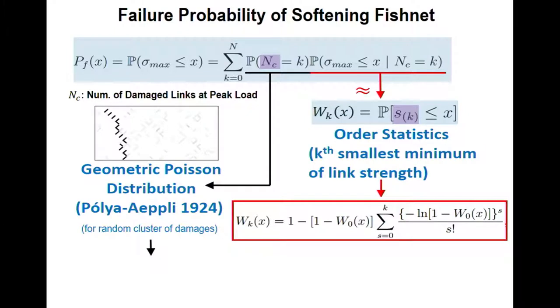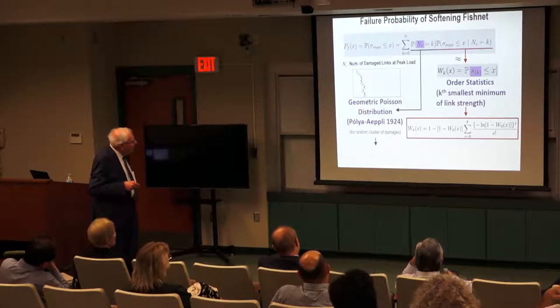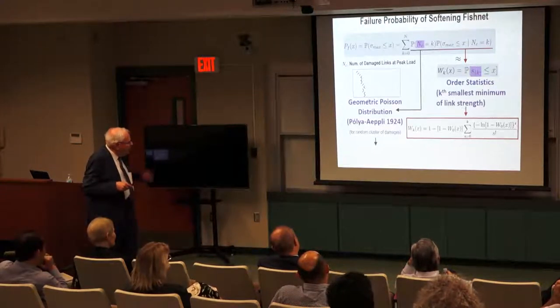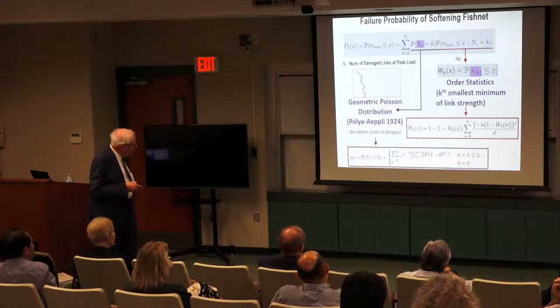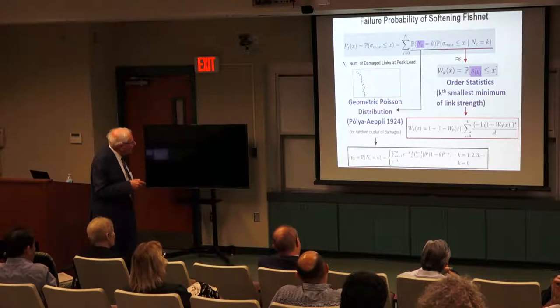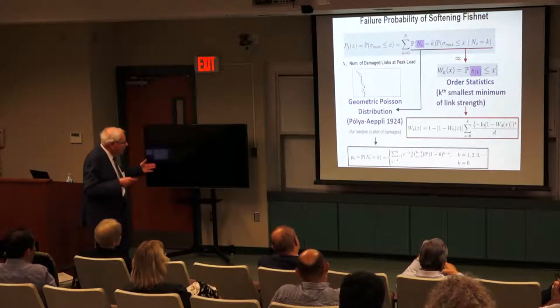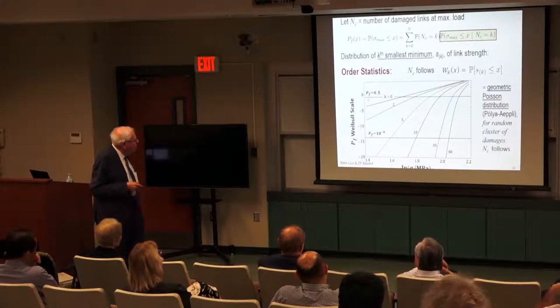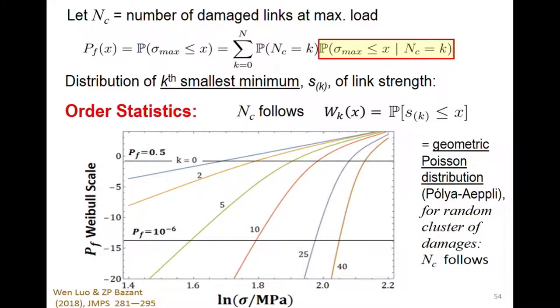All right, so the probability of failure is then the probability of how many jumps you have going down, which is a random number itself, and the probability, given that number of jumps K, conditional on the K-th minimum, that sigma is given, then the arguments, then the load. So order statistics, there are several books on it, gives you some formula, which is not difficult. That's here, how to calculate it. And for the distribution of the number of jumps, this is like arrival statistics, actually it's a geometric Poisson distribution, it's another formula. So that's what we discovered by reading more literature on this kind of behavior, and we put it into calculations. And then, using order statistics, we find the following.